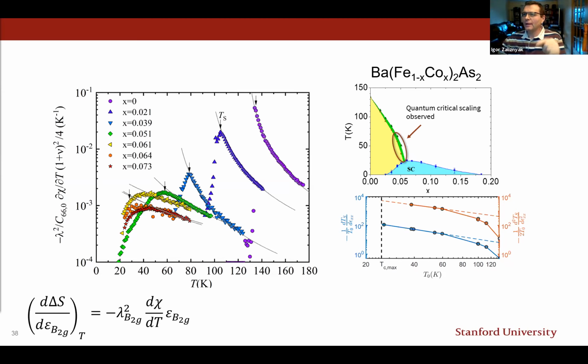Let me phrase it in another way. So you interpret all this evolution, and especially this giant elastocaloric effect in the parent material, as an electronic phenomenon. However, there are two parts to this question. One, am I right in thinking that the parent material is less of a metal than a doped one? And if so, then in a less metallic material, in an insulator essentially, there is a class of insulators which we recently called Coulomb floppy networks, to which these materials belong, because the tetrahedral coordination allows for under-constrained positions of some ions.